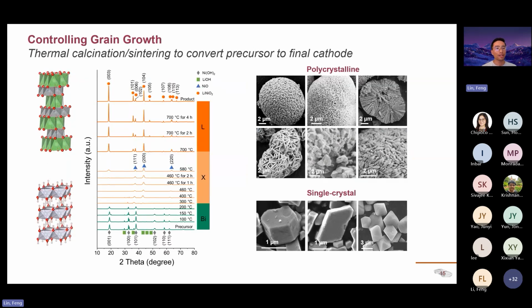So how do we do this kind of study? The first thing we usually do is control grain growth. In the figures on the right, there are SEM images of different types of microstructures that we have studied over the years. But the other thing is not just the morphological information. Morphological information will give us information such as tap density of the materials and the packing density, which is related to volumetric energy density. But we also want to understand how the phase transformation is happening.